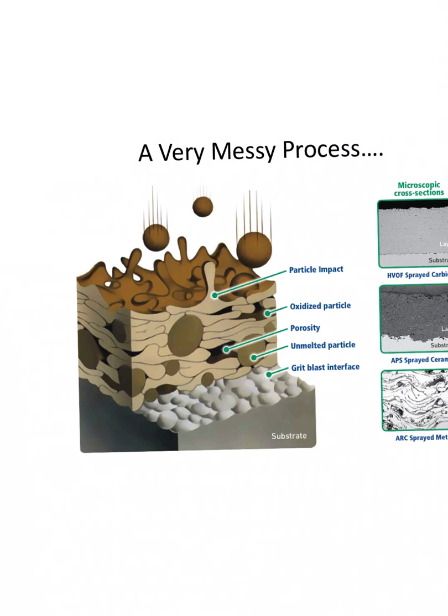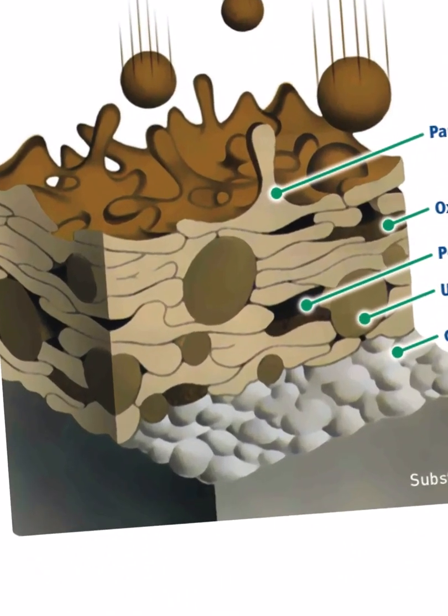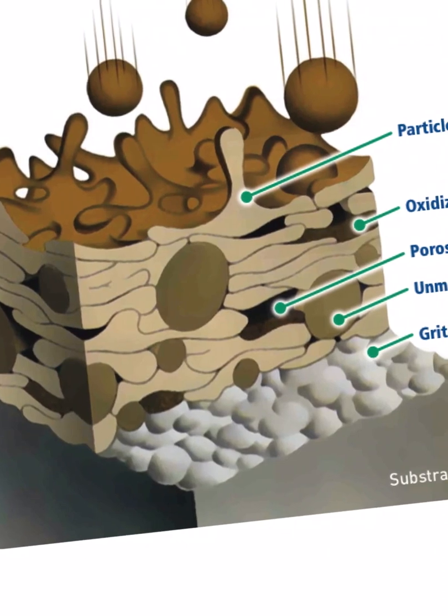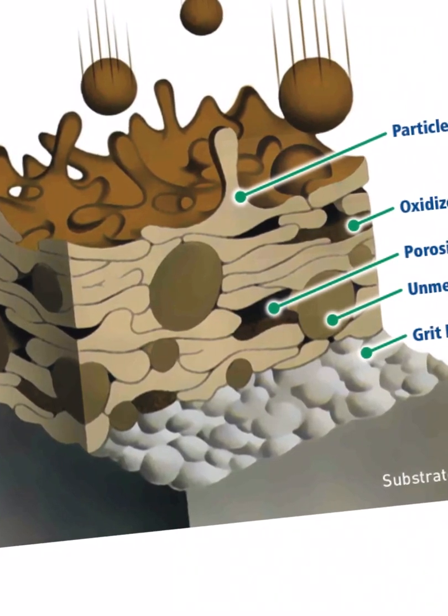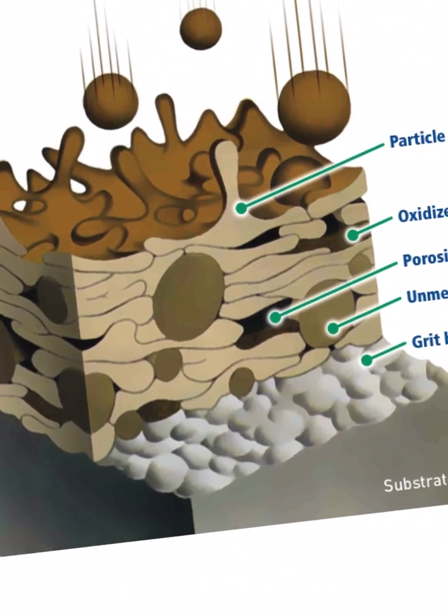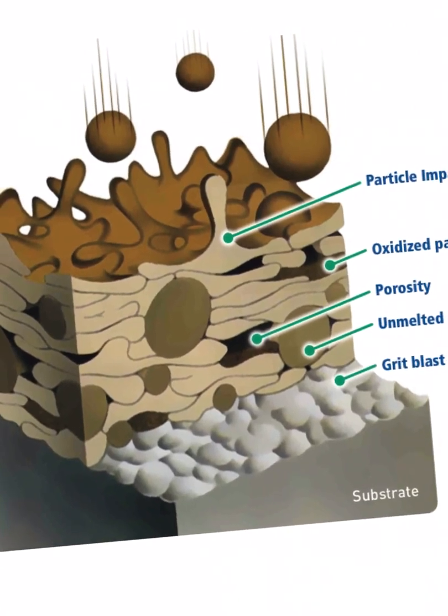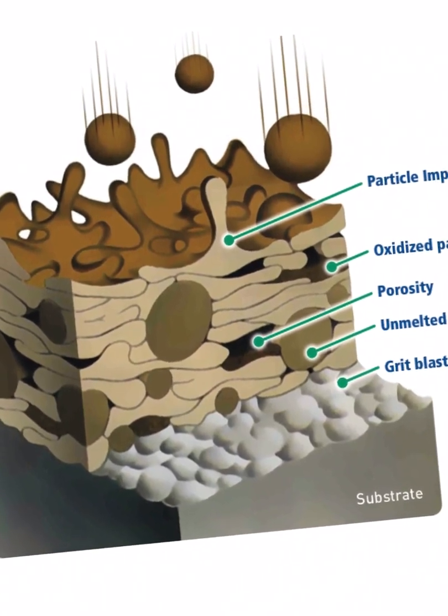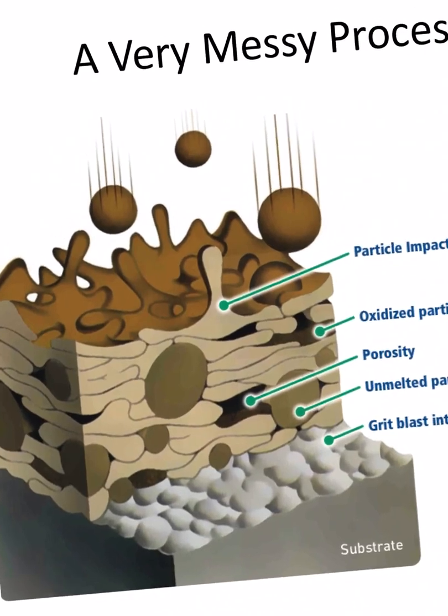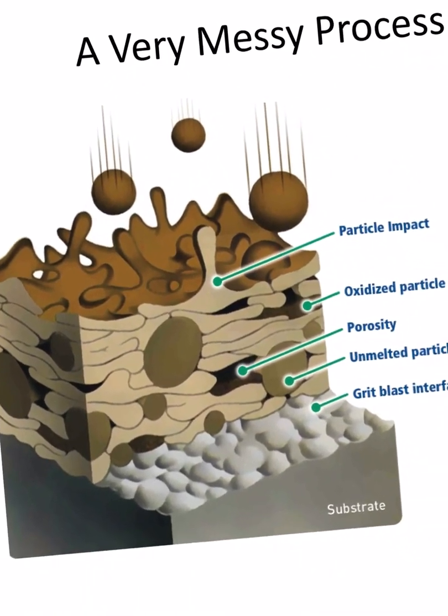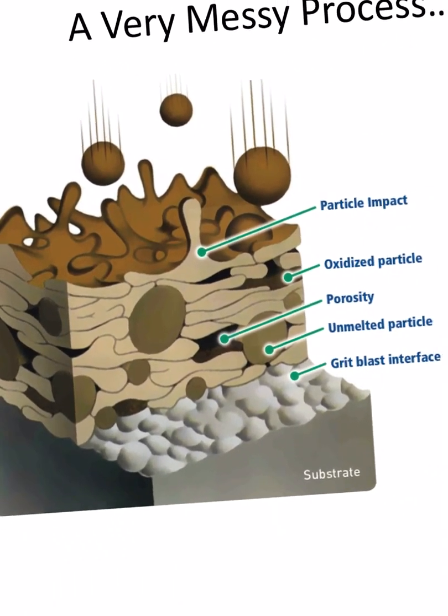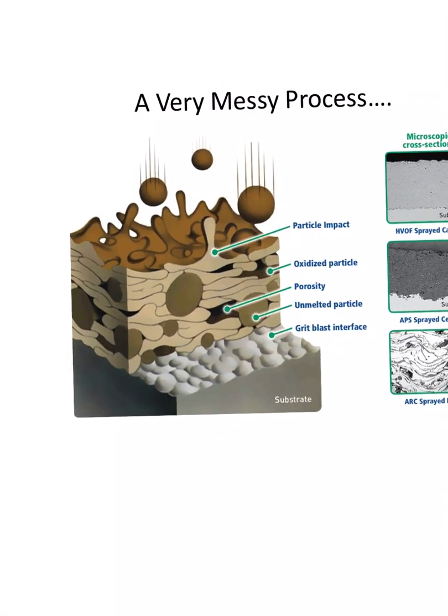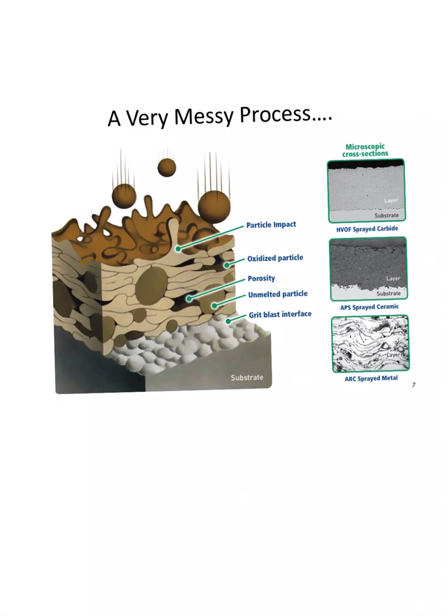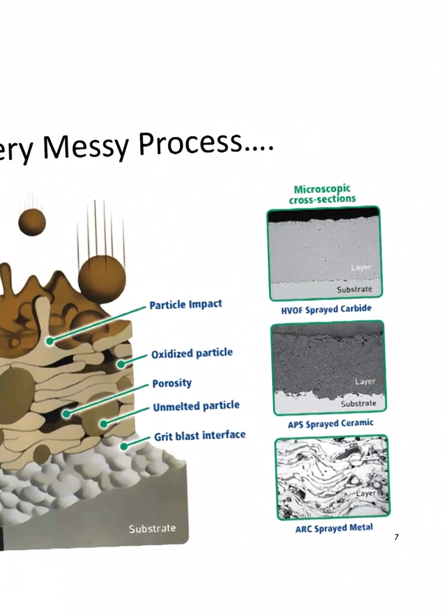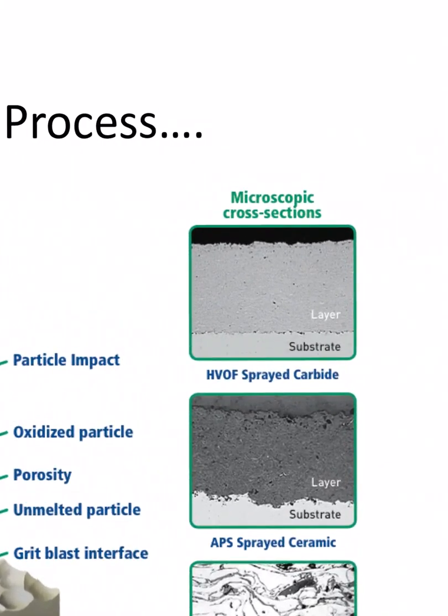And so what you see, though, in this context is some areas are made of individual splats, and you can see the fact that one arrived on top of that. Sometimes it doesn't splat at all because it came through the jet and didn't get as hot as it should, so you can have particles buried in there, and that's all happening on top of that. So it's a very kinetic process, as opposed to the thought you might have of making a nice uniform dense layer. And this is just showing you some examples in cross section.